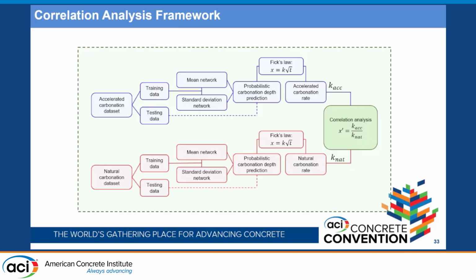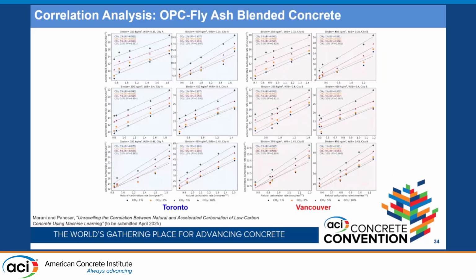So now that we performed that sensitivity analysis and we are confident in the accurate predictions of the model, we can go to the next step, which is to find the correlation between the accelerated and natural carbonation depths. With those carbonation depth predictions, we can use Fick's law, as I told earlier, to find the carbonation rates, and then we can find the correlations. In these graphs, we can see that if we divide different mixtures with the same binder content and the same water-to-binder ratio, but with different SCM replacement levels, we can find a relatively highly linear correlation between the accelerated carbonation rate, which is on this vertical axis, and the natural carbonation rate, with a pretty high R squared, as you can see here.